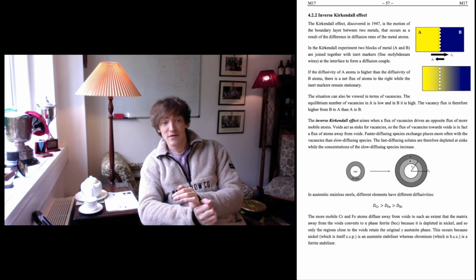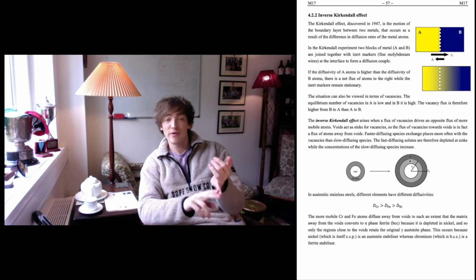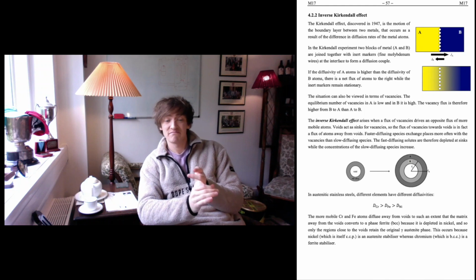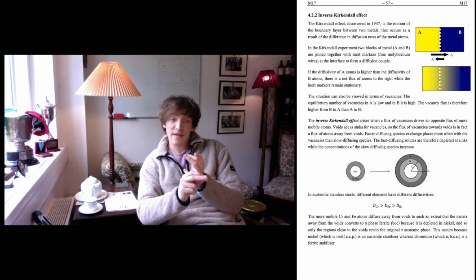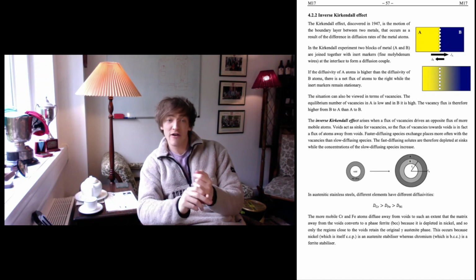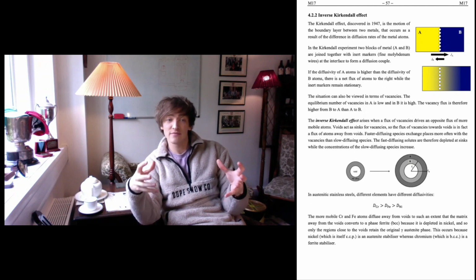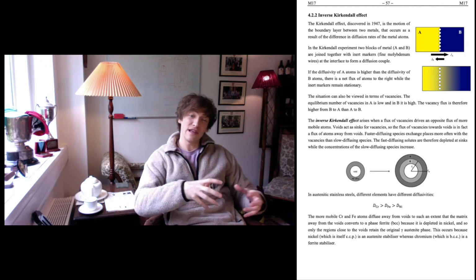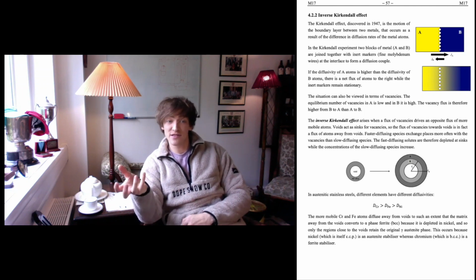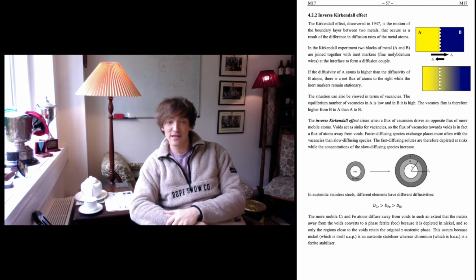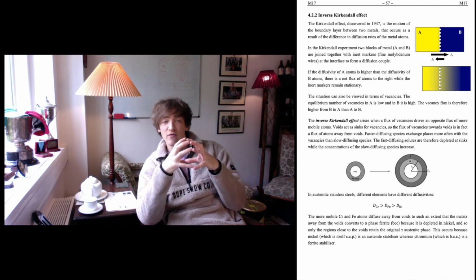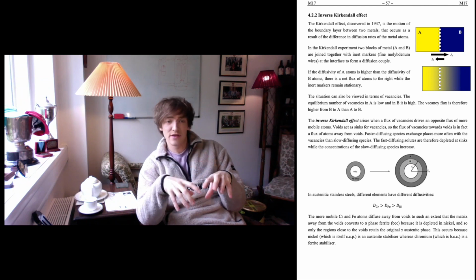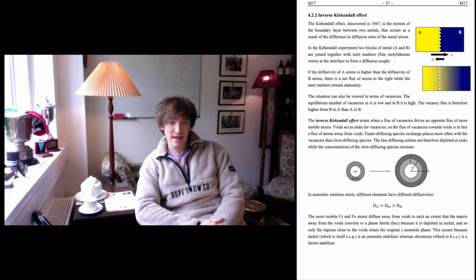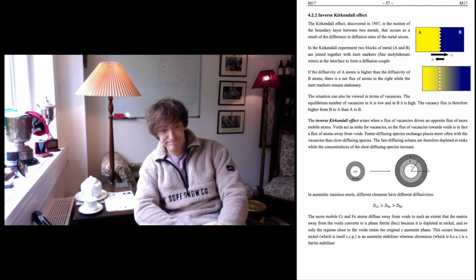In stainless steels, one of our main species, we've got chromium, iron, and nickel. Chromium diffuses faster than iron, and iron is faster than nickel. So if we're thinking about the inverse Kirkendall effect, that means chromium and iron diffuse away faster from voids and cause ferrite to form away from those voids as it becomes depleted in nickel. And that means that only regions close to voids remain austenitic, because nickel is an austenite stabilizer, and nickel is slow and stays by the voids. So you start to get the material around the voids staying as austenite, but the regions around it transforming to ferrite. And obviously ferrite has very different corrosion properties.